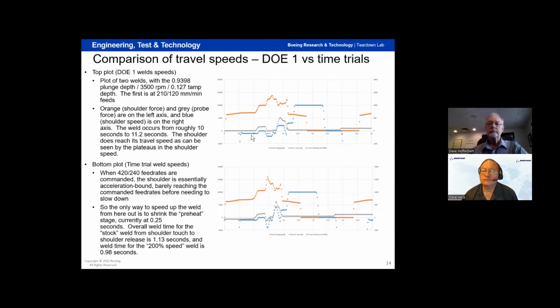And what he saw, so the original DOE welds were about 1.2 seconds long to do start to finish. Once you start plunging until you're pulled out of the part, was 1.2 seconds on those first DOE welds. And when he increased to a 200% speed, he got that down to a whopping 0.98 seconds. So we did get a 20% increase in speed, but again, it was still about a second long, which was much better than the 6 seconds or so that we had stated earlier.